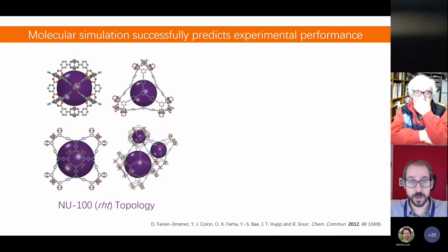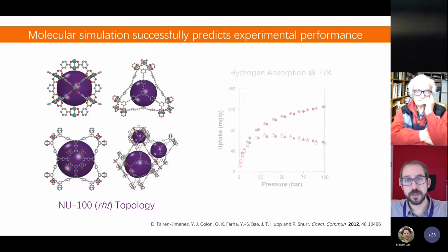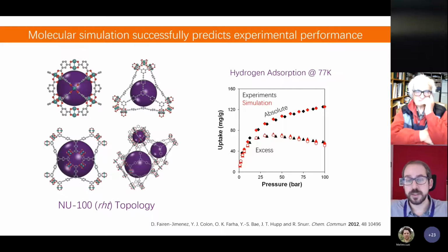We can run molecular simulations, as I said. We just take the structure of the material as an input file, and we can simulate the performance for hydrogen storage at 77 Kelvin. This is the uptake of hydrogen per gram of material when I increase the pressure. This is the absolute capacity, the excess capacity.